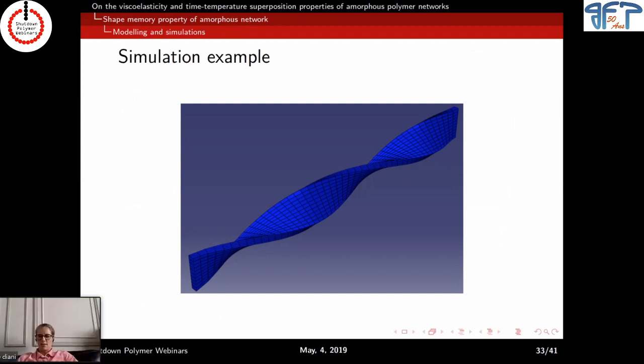So I think there's two things that are different. Yeah, you're right. Our model is really based on the glass transition temperature. And so if you look at TPE that you're using for shape memory property, if you have time temperature superposition, I think it should work, no problem. When you look at now crystalline material and look at the fusion and the property, it's another physics. And so probably you need another model, other constitutive equation, because the physics is completely off, right?